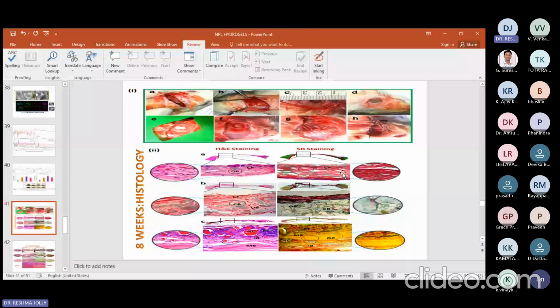We found that osteoblast formation was there when we filled the defect with Cerabone. And there was collagen fiber formation in the SR staining, which could be seen. But when we filled our defect with the material we formed in the lab, we found that after 4 weeks the mediated bone had started, and after 8 weeks you can see the mature bone has started forming.